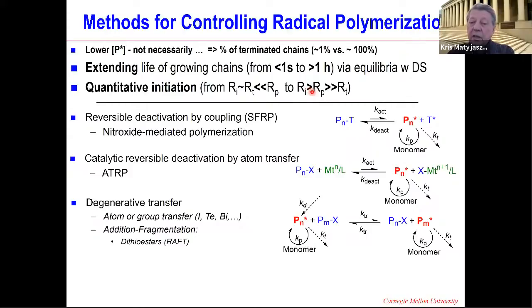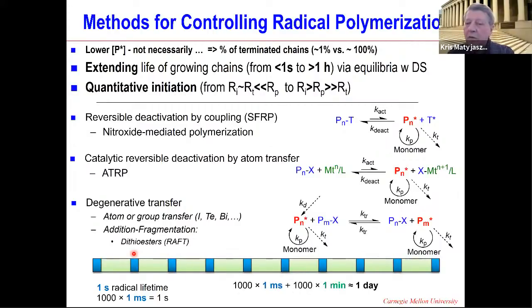In controlled processes, the rate of propagation must still be 1,000 times faster than the rate of termination, but the rate of initiation is independently controlled and can be faster than the rate of propagation, because the steady state of radicals is defined by this activation-deactivation process. So generally, in all of these systems, you could think that you take this 1 second life of a propagating chain, and then you divide it into 1,000 pieces, 1 millisecond each, and then insert within every millisecond of activity, let's say, 1 minute of dormancy. So now this 1 second is still 1,000 milliseconds plus 1,000 minutes, so essentially becomes equal to a day.